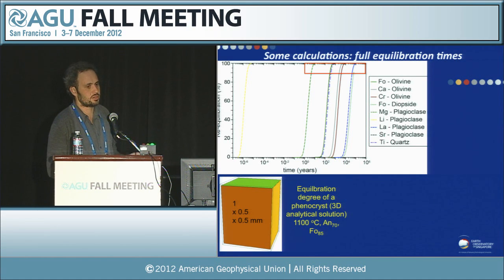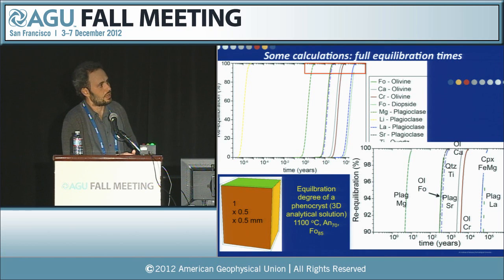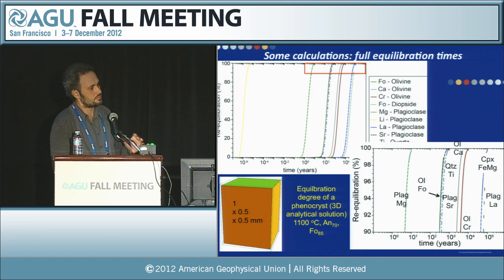A back of the envelope calculation would be this one, where we have equilibration of a crystal in 3 dimensions, a kind of ideal phenocryst, if you want, of these sizes, where we have calculated how long it takes to nearly fully reequilibrate these different elements, and here's a blow up. For example, if you want 90% reequilibration of magnesium in plagioclase, you can do this in a few years. Forsterite in olivine, you can do it in a few hundred, and then plagioclase strontium would be similar, etc. So it shows that in a few hundred years, you could completely homogenize some of these elements.